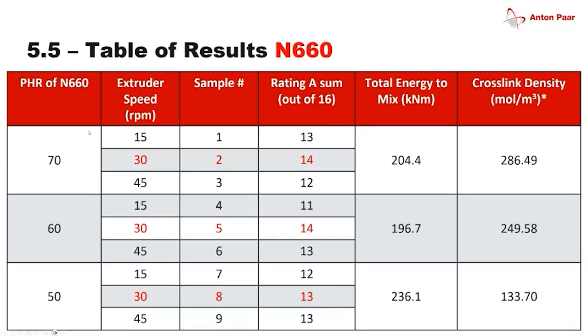So we have the different samples. Again, this is all for N660. And I highlighted the ones that I deemed to be best, also based on this rating sum. As an overview, I also added, because we measured this here, what was our cross-link density and what was our total energy of the mix. We can tell that this was the highest cross-link density, of course, at the highest fill. There's more chances of links to interact with the elastomer chains if you obviously have a high load.